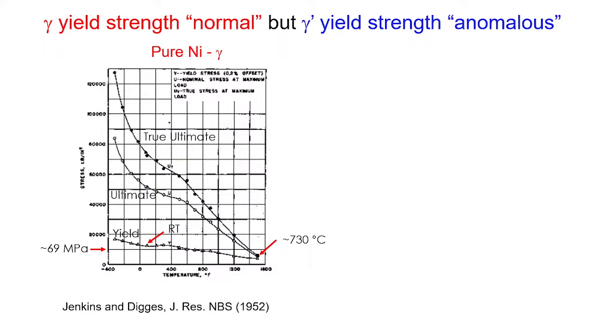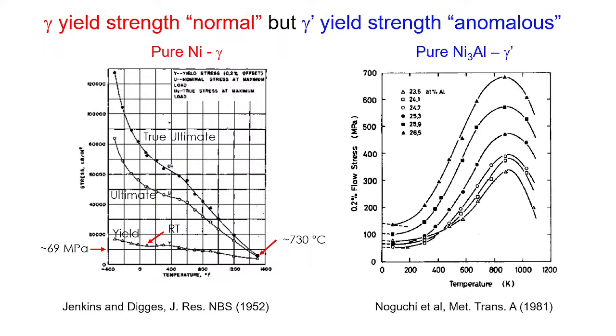But this gamma prime does the opposite, right? So this is this nickel to aluminum gamma prime ordered phase. Here's how its strength increases with temperature. So you have the best of both worlds, in the sense that you have a strengthening precipitate that actually gets stronger as you heat it up, and you have a matrix that remains ductile over the entire temperature range. And that's why these two-phase alloys have been so successful.